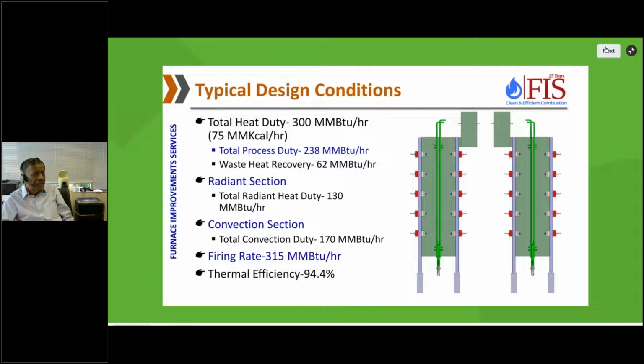This is a typical design of a cracking heater. Duty is about 75 million kilocalories, 300 million BTUs. Total process duty is around 240. Waste heat recovery is around 62. Radiant section heat duty is around 130. So you can see about 42, 43% is the radiant duty in the radiant section, and the rest is in the convection section. So the convection section is bigger actually: it's 170 million BTUs, radiant is 130. Firing rate about 315, and the efficiency you can see is almost 94, 95%. So very, very good efficiency is typical in cracking heaters.